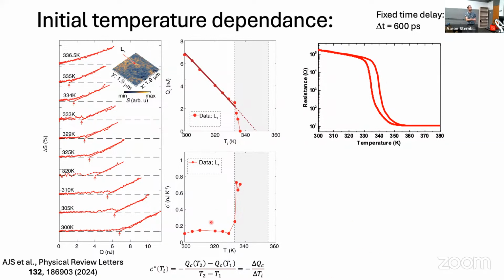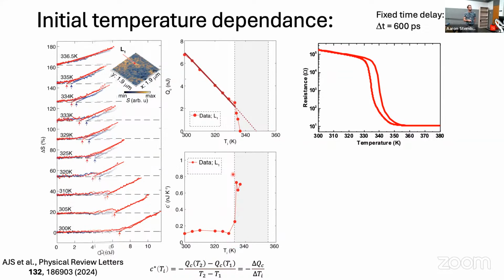We can also analyze a slightly different quantity, which is how much the fluence threshold changes at two neighboring temperatures, which we called the photothermal capacity, or C star, in this work. The reason for that I'll explain in some detail. Essentially, we see that this quantity is more or less flat until a certain temperature when there's an abrupt increase or divergence of this quantity.